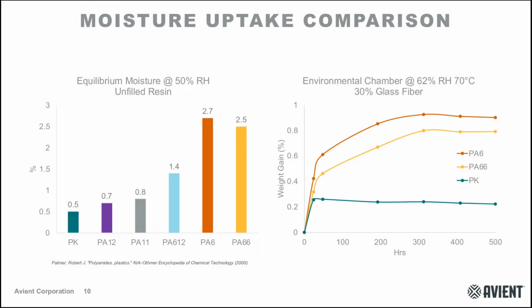And you can see the relative properties of moisture uptake in the graph on the left. Here we're looking at unfilled resin at equilibrium moisture, so it's 50% relative humidity. In this case, basically a higher bar indicates the material is taking up more moisture. Unsurprisingly, nylon 6 and 6/6 take up quite a lot of moisture, and you see that in the resultant properties, whereas these long chain nylons take up less moisture, and polyketone actually takes up the lowest at 0.5%.